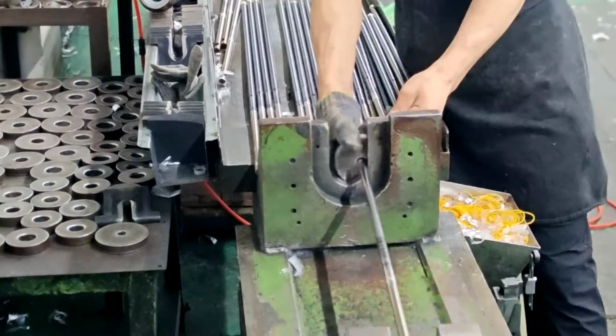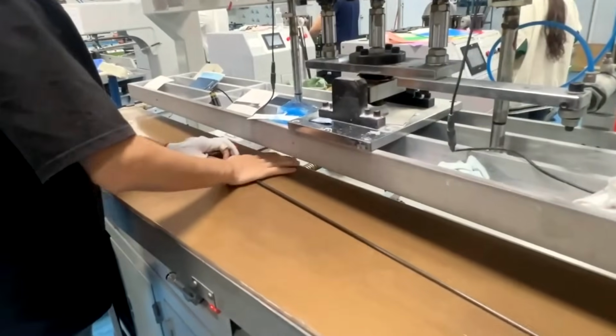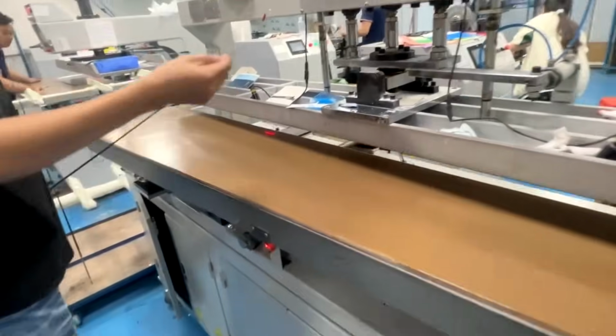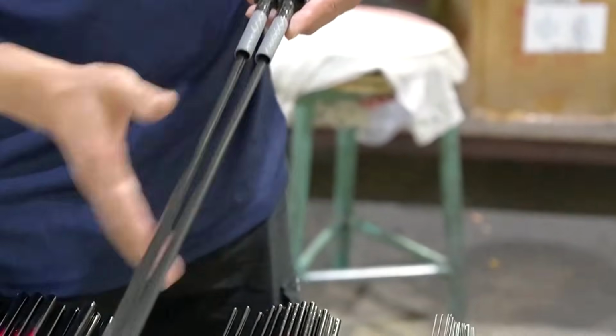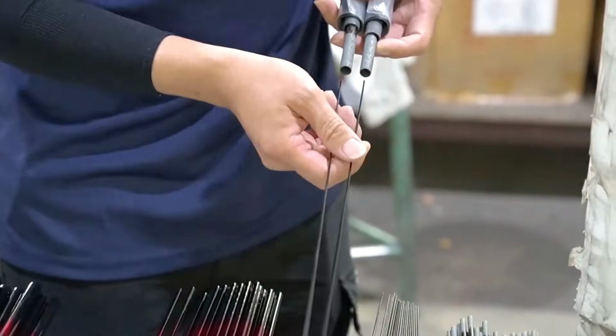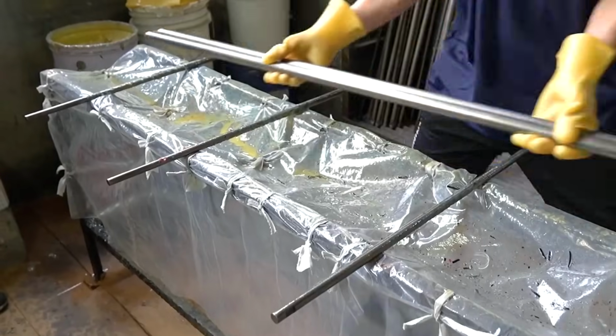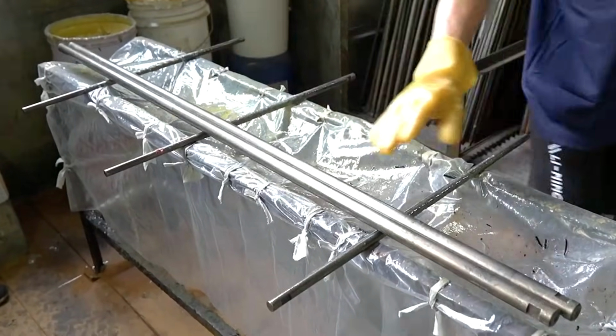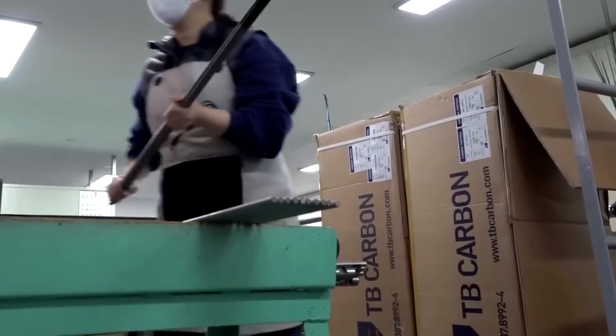After the surface is finished, the sections are moved to the joint fitting area. The technician inserts the tip section into the butt section to check the orientation and the physical integrity of the connection. 0.04 of an inch is the maximum deviation allowed at the joint before the continuity of force transfer is disrupted.